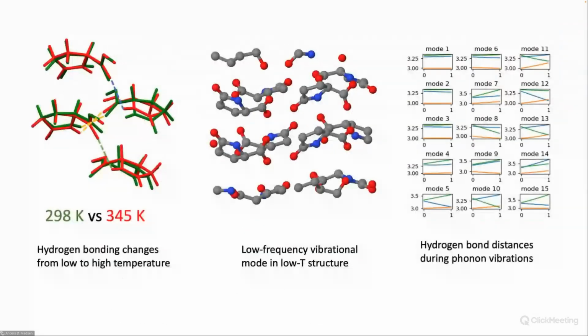So what's going on in this case? The two forms are quite similar, but we go from the low temperature phase, which is the Z prime equals 3 case, so 3 molecules in the asymmetric unit, to the high temperature phase where we only have 1 molecule in the asymmetric unit. And this breaks a certain number of hydrogen bonds. So the hydrogen bonds that are present in the high temperature phase are not all present in the low temperature phase. As you can see over here, the high temperature phase is the red model, and it has got these 3 OHN hydrogen bonds, I think, or ONH hydrogen bond it is. Whereas some of those are broken in the low temperature phase.